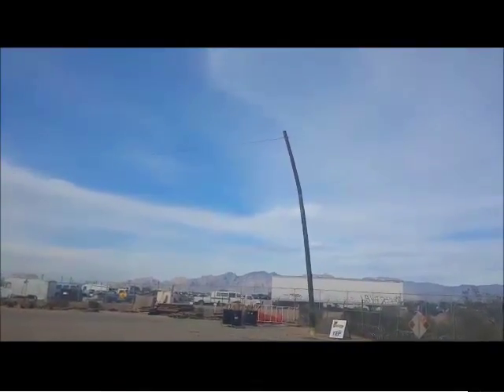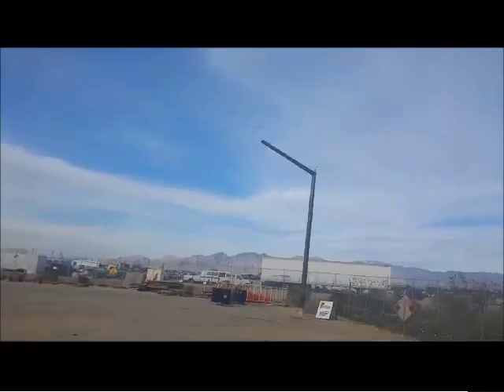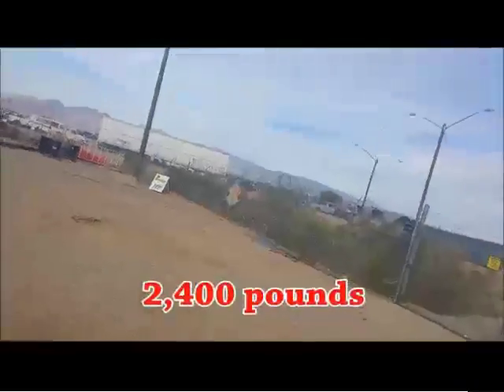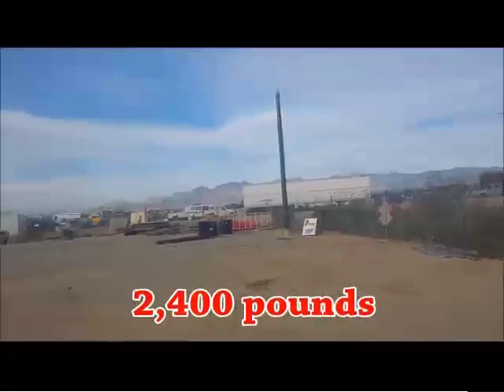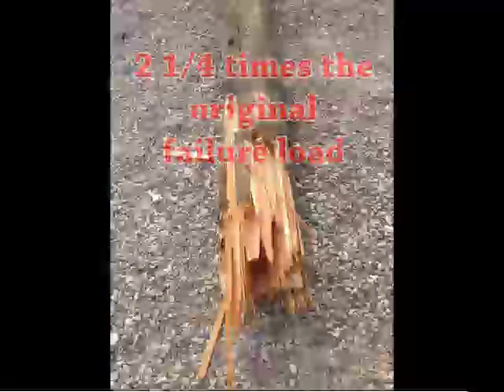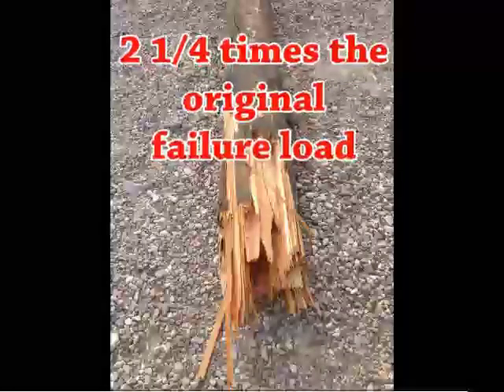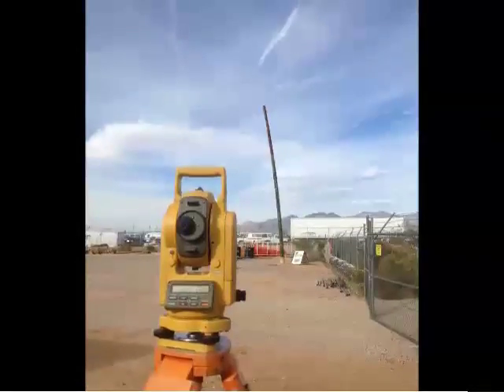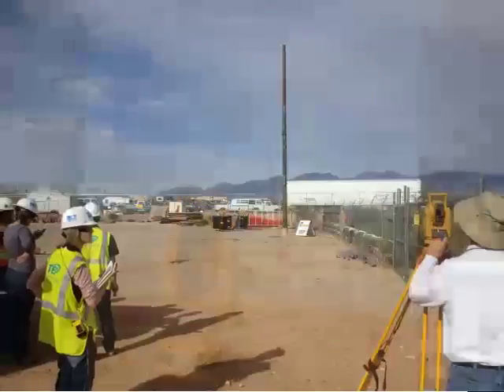The strengthened pole was tested, and it broke at a load of 2,400 pounds exactly at the point where the repair had stopped. This load was 2 1/4 times the original failure load. We are conducting additional tests to develop design guidelines for such repairs.